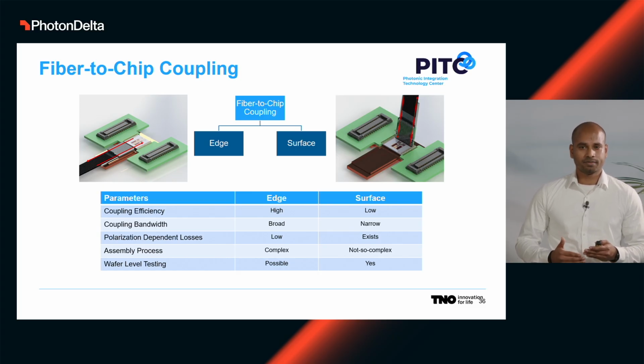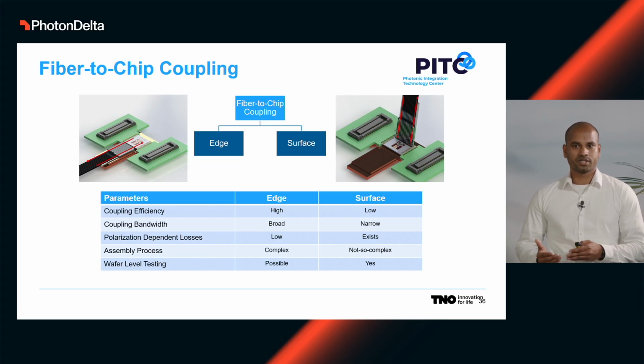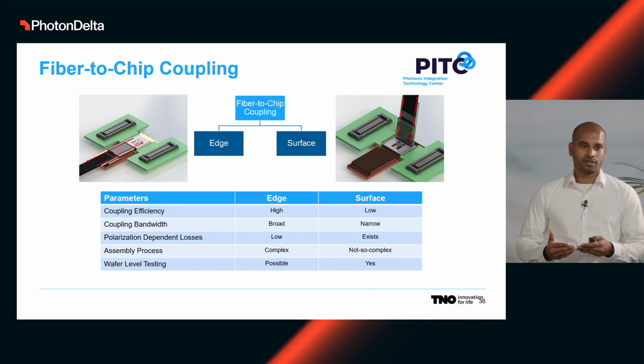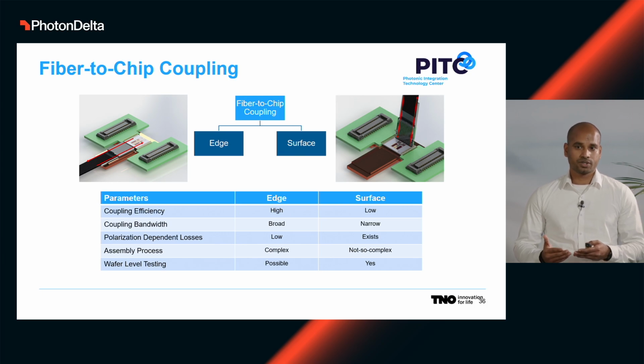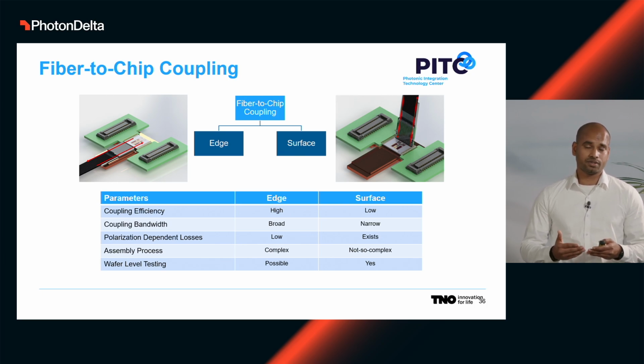at the back end, it becomes a bit complicated with edge coupling, especially if you need polishing and also if the mode-field diameter is too small. But it's not the case with the surface couplers, because the grating couplers are much more alignment tolerant, and also there is no need of a polishing step. In addition to that, surface couplers enable wafer level testing, so you can already test the wafers and find the known good dies before you actually package them. It's now also possible with edge coupling, with an additional step of having a trench.